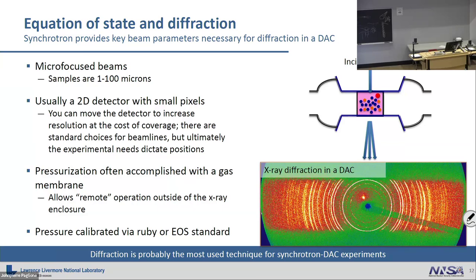So we often use noble gases. The one of choice is neon for us. Helium is great. It's more hydrostatic for longer, but it has the problem of intercalating things. It was mentioned that over time you can intercalate the diamond, but if you can intercalate diamond, you can also potentially intercalate your sample with helium. So you can get some kind of weird things where you push helium into the sample depending on what it is. Neon's a little bit bigger, it usually doesn't have that problem. We use argon sometimes, and that's probably about it for the noble gases. All of those freeze by 30 GPa, so everything above 30 GPa is frozen all the time, at room temperature.